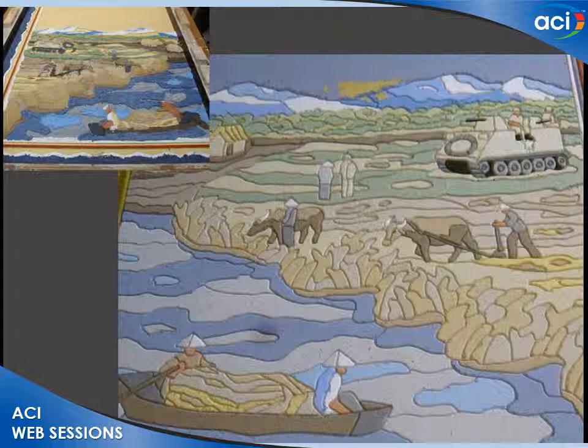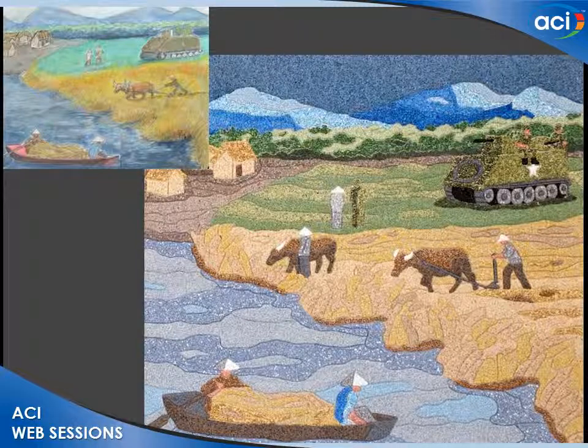On the upper left, you can see it as we're placing the concrete into the mold, and in the large one is when we take it out of the mold. It's very chalky, pasty, cement-looking, because we have not exposed the aggregate. But you can clearly see the grooves that are left where the ridges were. We used a high-density urethane foam for the molds and a retarder that we sprayed on, a foam retarder.